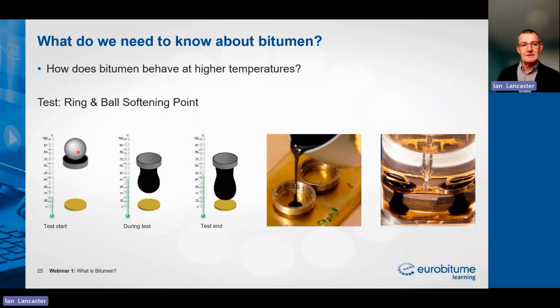And as the bitumen starts to heat up, the ball, which is placed on the surface of the bitumen at the start of the test, will start to sink through the ring. And when it touches the bottom, that's the softening point, the ring and ball softening point. And that gives us an indication of the high service temperature end of the bitumen. And we need to know that to make sure that the bitumen will perform at high temperatures.